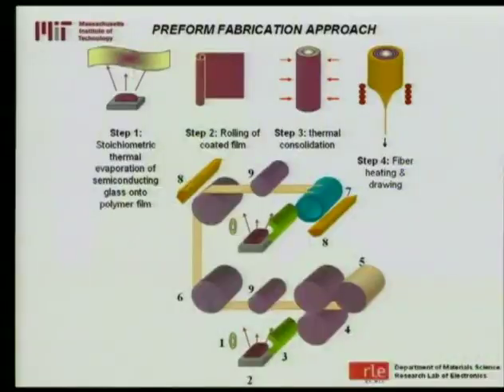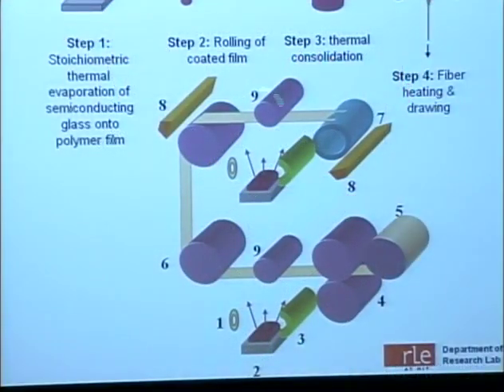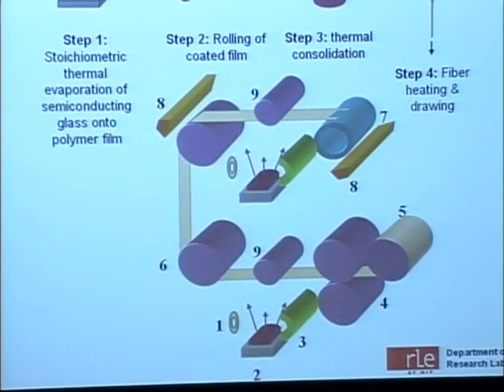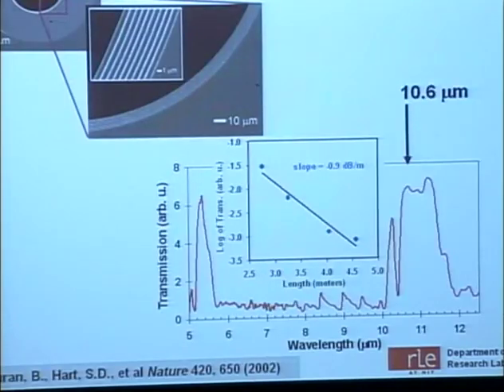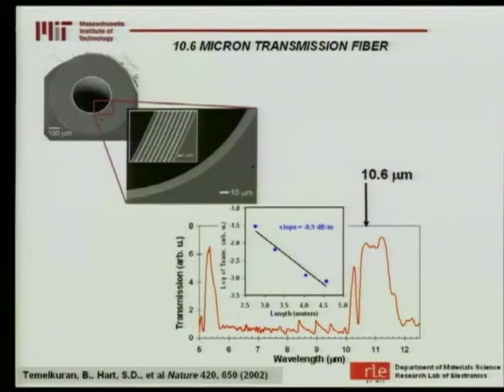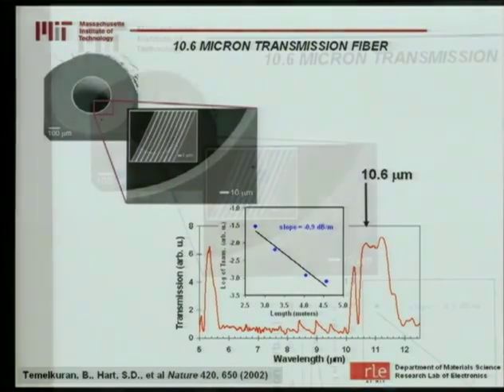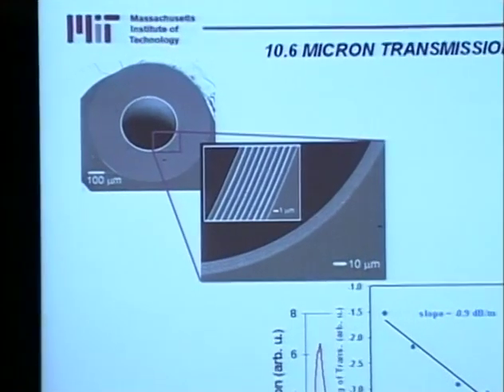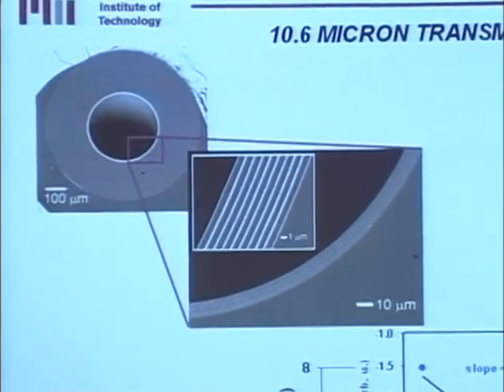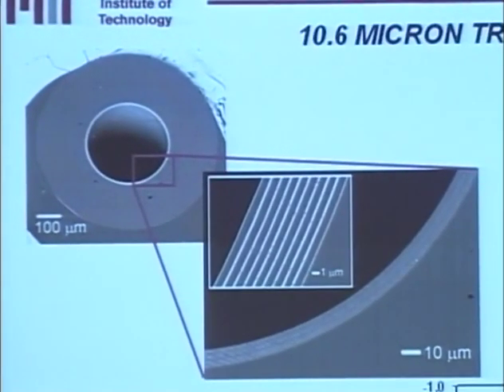What we then also did was develop a fabrication technique, which is a roll-to-roll technique where we take a feed of the polymer, evaporate the semiconductor on it, roll this up into a preform, and then draw it into a fiber. Basically, this is what the result is. We have a fiber that has this multi-layer dielectric, has this photonic band gap that is omnidirectionally reflecting, confining light now in a hollow core. And the beauty of this is that you could now decouple the problem of transmitting light from the problem of finding transparent materials.